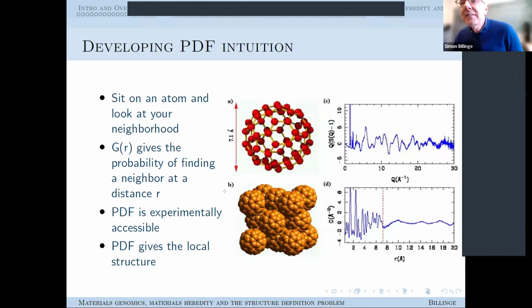The one-dimensional PDF is the one that we deal with experimentally much more frequently, and this is where we have a sample which is made up of not a single crystal, but a lot of small crystals all randomly oriented. And so we do an orientational average of the 3D PDF. What you get is a one-dimensional function which has peaks at certain positions corresponding to interatomic distances. So if you sit on this atom and you go to this one, it's 1.4 angstroms away. In C60, it's a carbon-carbon bond, and here's a peak at 1.4. This is the second neighbor distance, and the second peak is at 2.5. This is the third neighbor distance across the hexagon, and it's at 2.8.